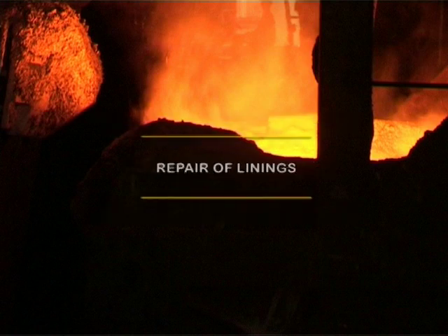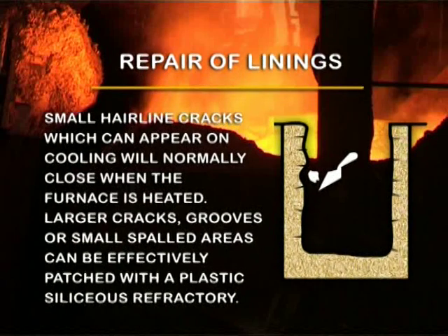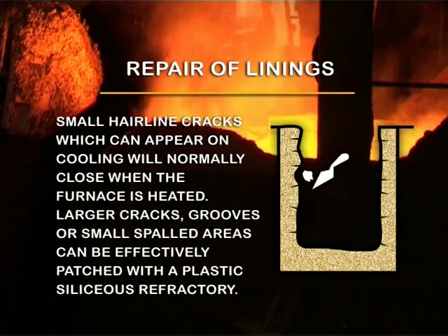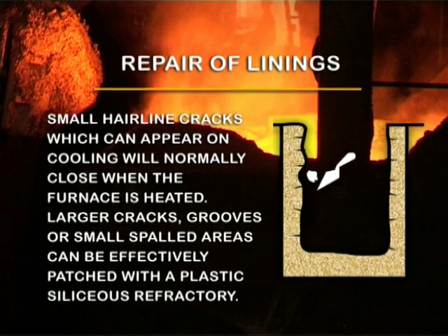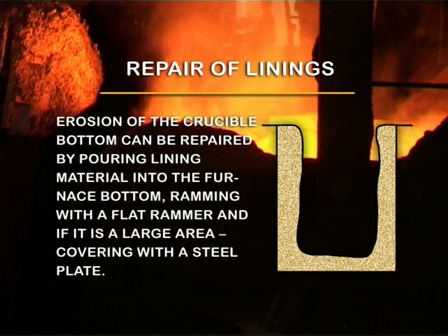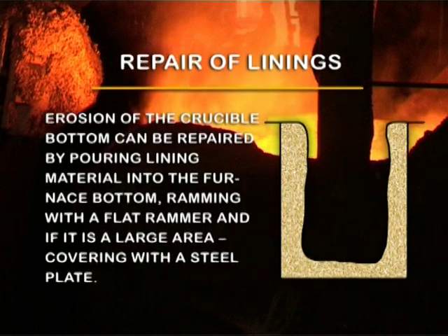Repair of linings. Small hairline cracks which can appear on cooling will normally close when the furnace is heated. Larger cracks, grooves or small spalled areas can be effectively patched with a plastic siliceous refractory. Erosion of the crucible bottom can be repaired by pouring lining material into the furnace bottom, ramming with a flat rammer, and if it is a large area, covering with a steel plate.